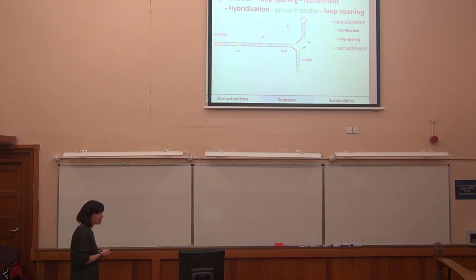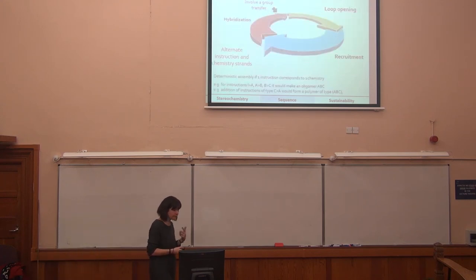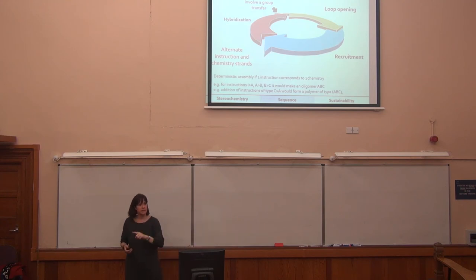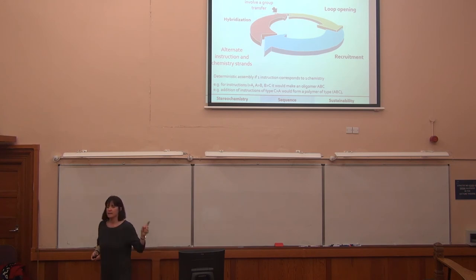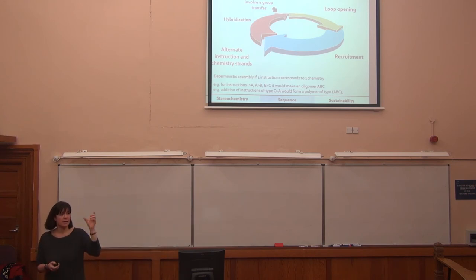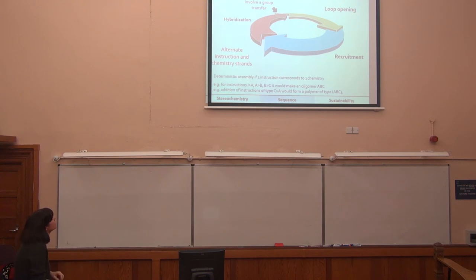So we have this cycle of hybridization, loop opening, recruitment, and this cycle opens a loop and then instructs the next thing to add to an instruction, and then addition of chemistry. And that allows us to then build up this mechanism. So if we think we have these cycles of hybridization, loop opening and recruitment, one cycle essentially is the instruction cycle, the next cycle is a group transfer. So we have to do this twice to be able to add a monomer unit. So it's quite complicated, but it works.